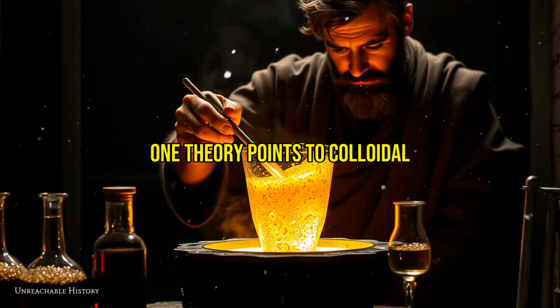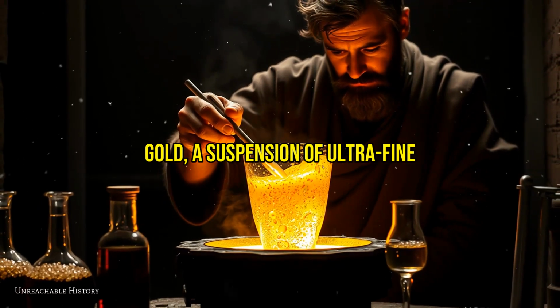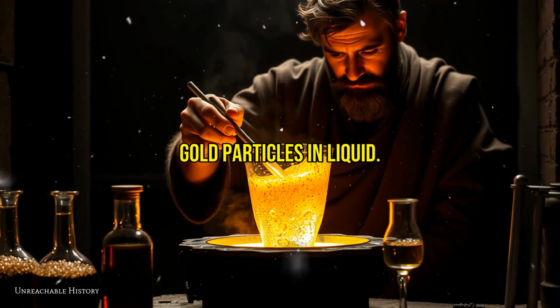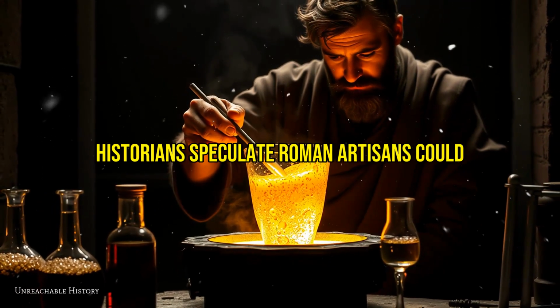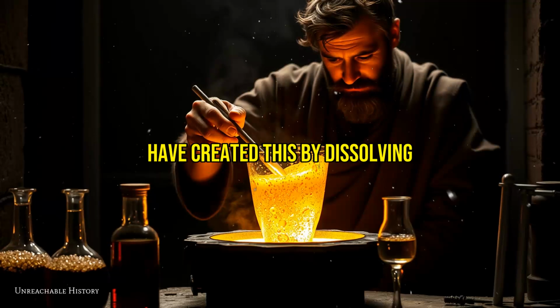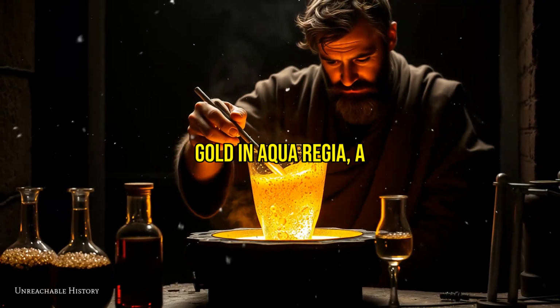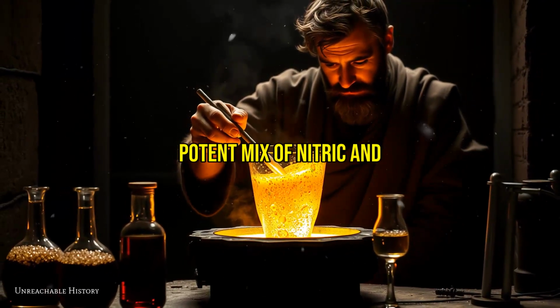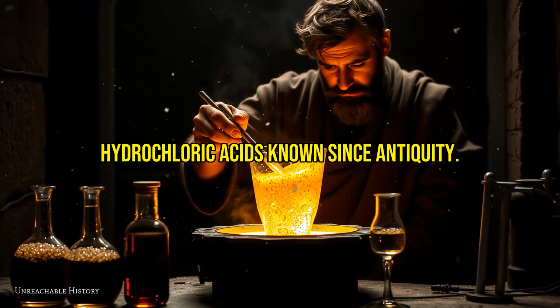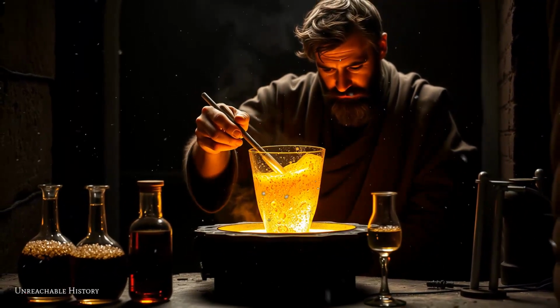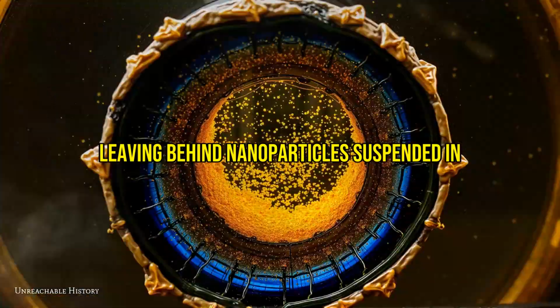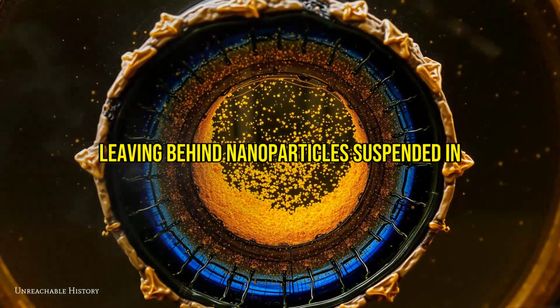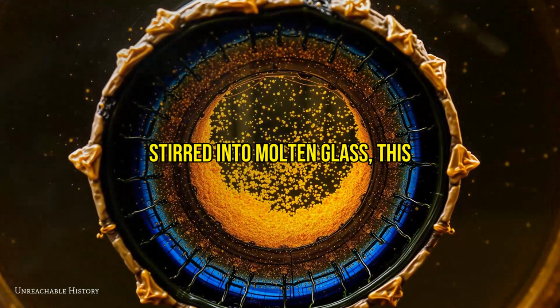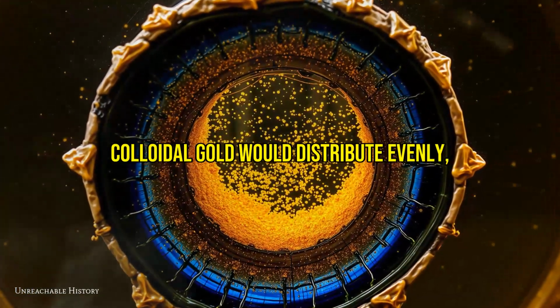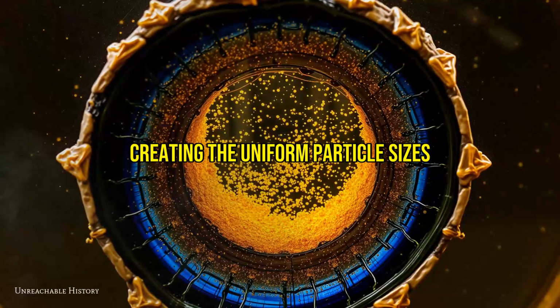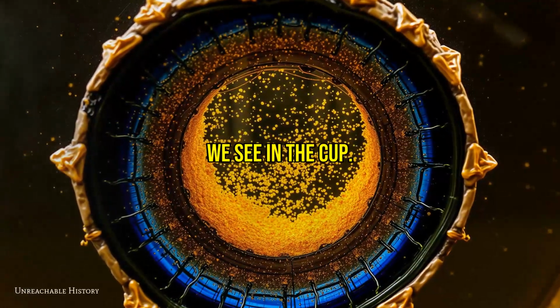One theory points to colloidal gold, a suspension of ultra-fine gold particles in liquid. Historians speculate Roman artisans could have created this by dissolving gold in aqua regia, a potent mix of nitric and hydrochloric acids known since antiquity. They'd then reduce the solution, leaving behind nanoparticles suspended in liquid. Stirred into molten glass, this colloidal gold would distribute evenly, creating the uniform particle sizes we see in the cup.